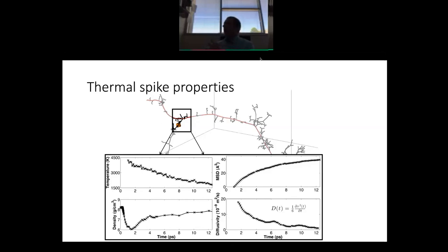Now, how quickly would that couple back to the lattice in a metallic glass? I don't know. Electron-phonon interactions in metallic glasses, if memory serves, and please don't quote me on this, are somewhat less efficient than in the case of crystalline metals. So I would expect that coupling to be slower. However, those things would eventually couple back. Of course, before they couple back, they would also have a tendency to conduct away through the electrons. And so I guess the question is, what volume of the material would actually see any energy coupling back from the electrons? I don't know the answer off the top of my head. Okay, but hopefully some of this stream of consciousness rumination gave at least a little bit of insight.